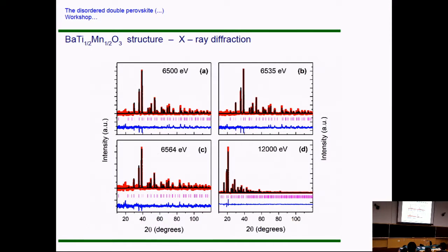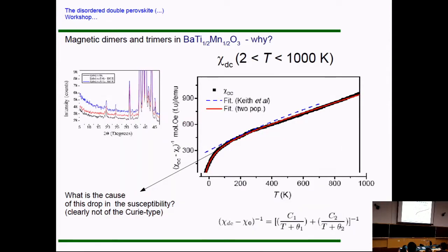We are doing pretty much the same thing with XAFS, right? And we always get something which supports the idea of that mixed occupation. That's the best you can do. That's the best we can do for now. So if you believe that we have this structure, we start to think about the magnetic properties. So here is a really broad overview, in this temperature region, of the susceptibility.